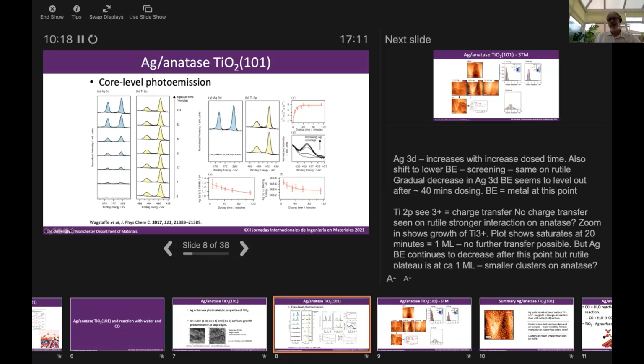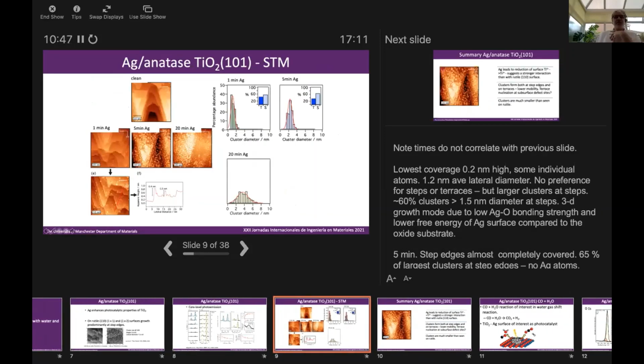And we see that after about 20 minutes of dosing time, we hit a maximum increase in this. So this suggests that this is where we form a single monolayer. Beyond this, we're just adding more silver to the surface, and we don't get any more changes in the work function, or sorry, in the charge transfer into the surface. So this was quite interesting, just from a fundamental point of view. We wanted to go on and look a bit more at the structure of what was happening.